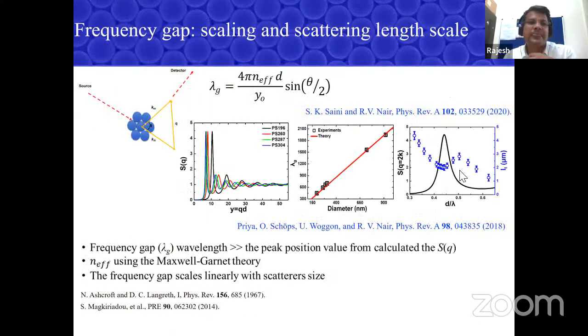To analyze that, we even developed a scattering model following these papers, and we came up with a small set of equations by calculating the structure factor, because if there is diffraction, there will be a peak in the structure factor. And you calculate the wavelength of the gap, the frequency gap, and plot it against the diameter of the sphere. So you can see that like a photonic crystal, which I showed you, the frequency gap wavelength for the short range order sample also scales linearly.